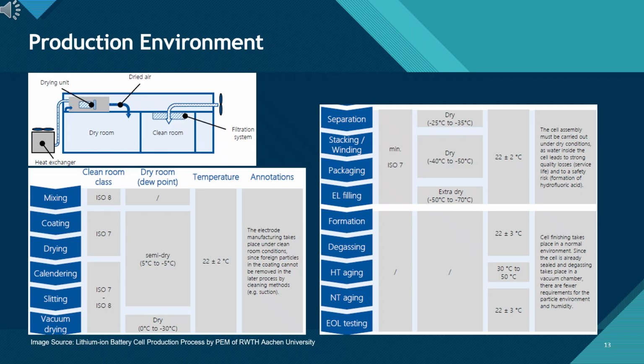Moisture control becomes increasingly strict as we approach cell assembly. The stacking/winding, packaging, and electrolyte filling areas operate in dry rooms with very low dew points, as low as -70°C, because even trace amounts of water react with the electrolyte to form HF, which reduces service life and poses a safety hazard. After cells are sealed, the requirements ease. Formation, degassing, and aging take place under controlled temperature and monitored safety systems, but no longer require extreme dryness.